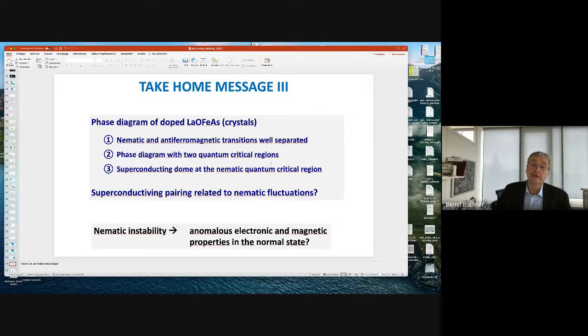And just looking at these crystals here, again, these are the systems showing the highest Tc, these are the systems showing the strongest coupling between all the degrees of freedom. If you just look at these systems, we would say, yes, nematic fluctuation seems to be very important. However, probably the situation is, of course, more difficult. And now I show you again some more elaborate work trying to understand this nematic instability.